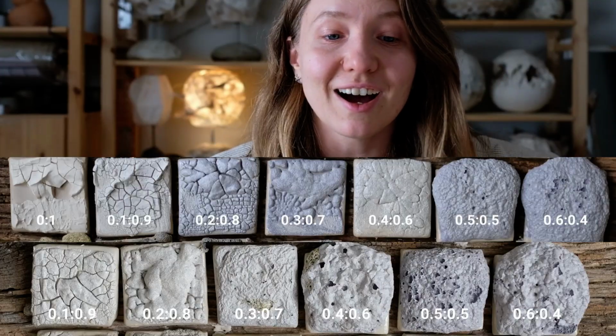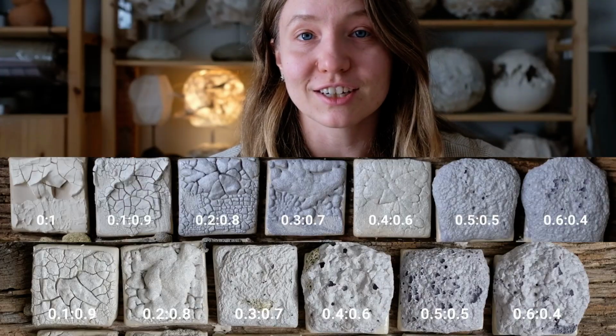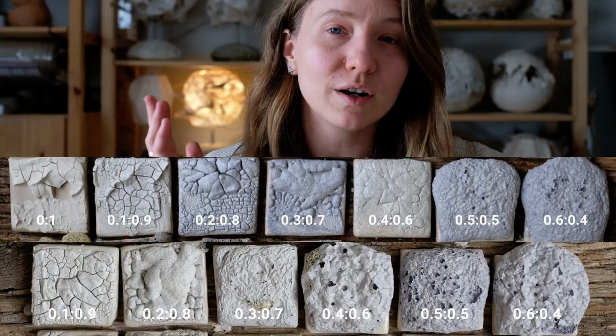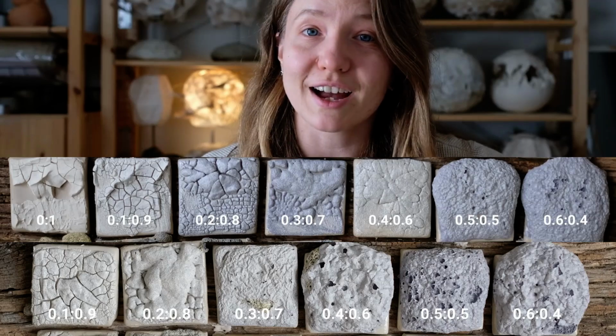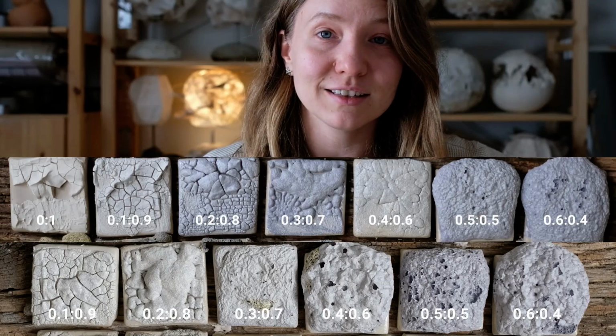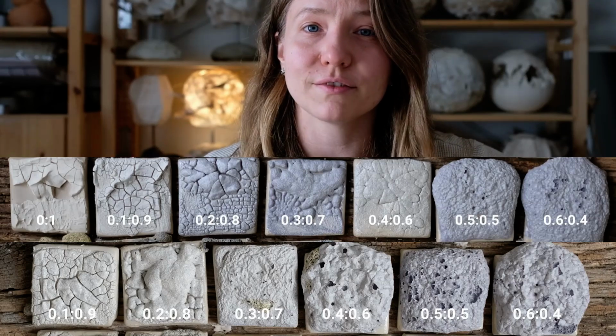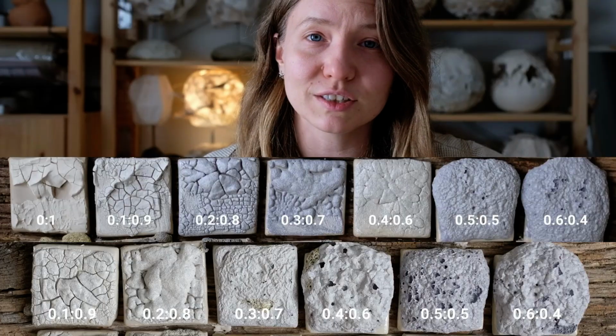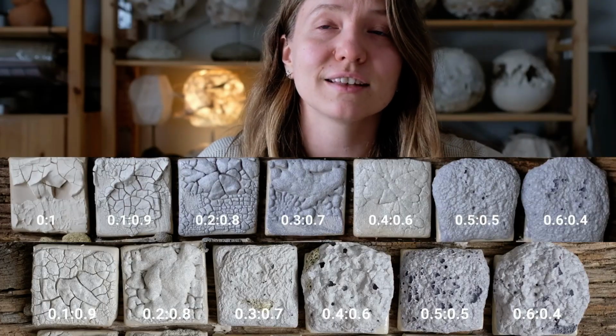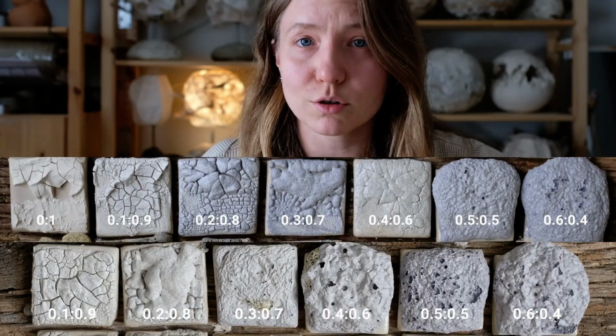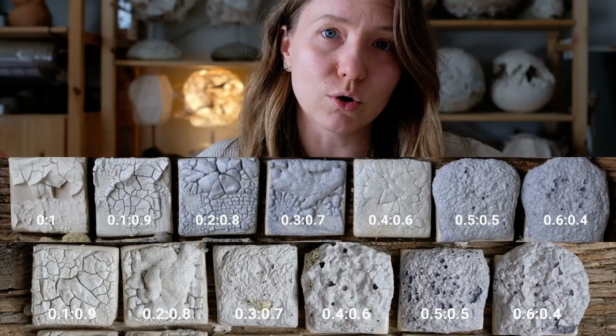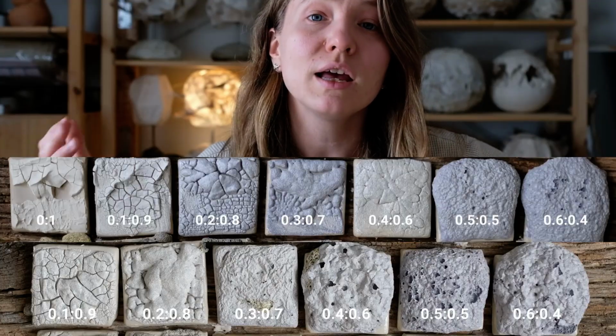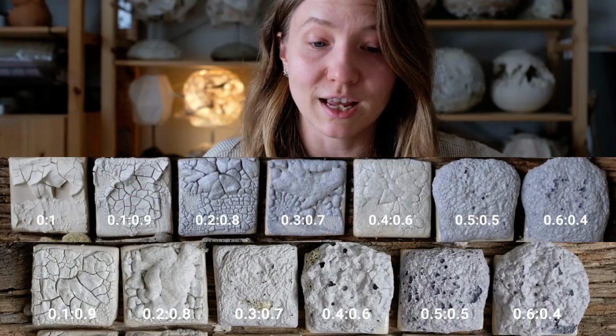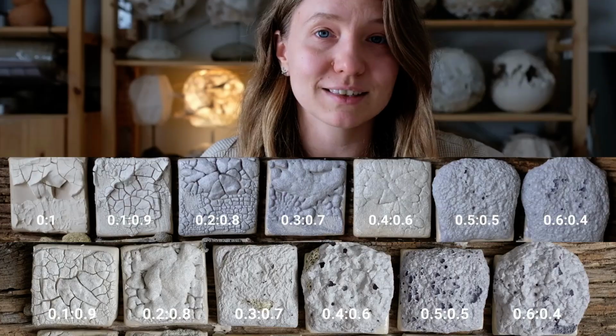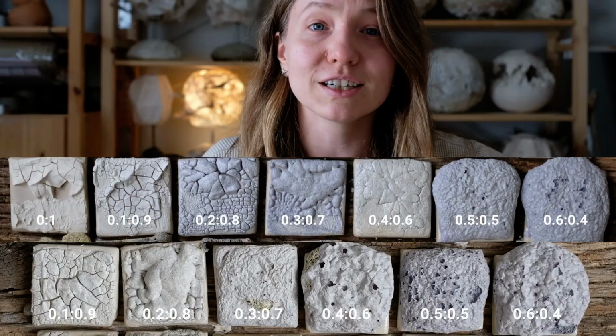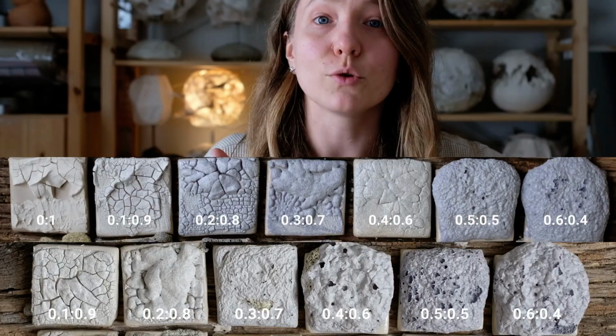As you can see, there are some really interesting results. So first of all, the more R2O we added, the more reaction we got. And this is easily explainable because feldspars, and Nepheline Syenite in particular, is a flux that facilitates melting because it's a more powerful flux. The more R2O or Nepheline Syenite I put, the more the reaction occurred. And in our case, reaction means both melting and also releasing carbon dioxide gas from silicon carbide.